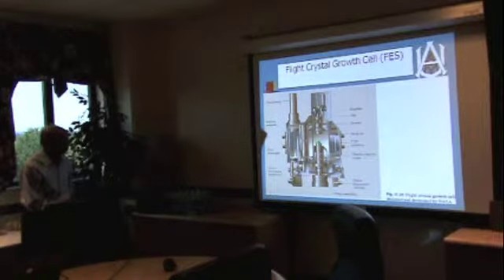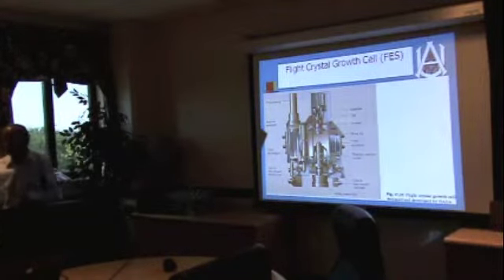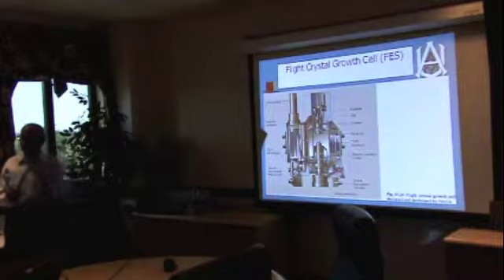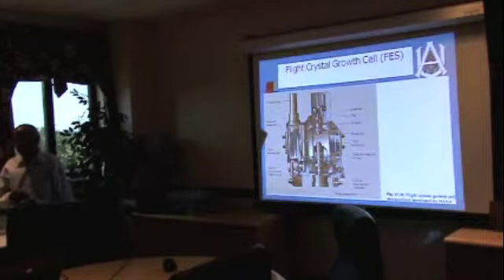So we have to develop a technique by which, after the growth is complete on this seed crystal, this thing is actually electrically driven by motor. This comes down and fits over the seed crystal. And there was a little balloon inside this, which you see here, the white thing. The purpose of the balloon was to push the fluid on the top surface of the seed, so that it drives the fluid out and then covers and seals it completely so that it stays there till the shuttle lands on the ground. And then we take this whole cell out and then remove the seed crystal. Yeah. So this is a sophisticated cell.